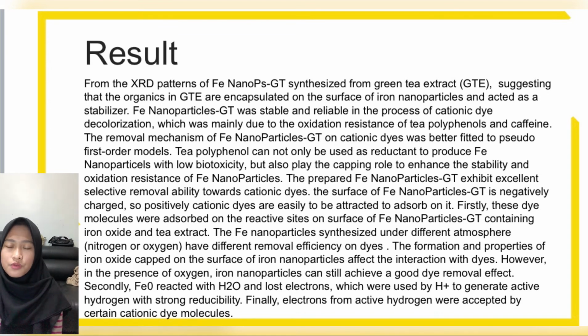synthesized under different atmospheres, nitrogen or oxygen, have different removal efficiency on dyes. The formation and properties of iron oxide capped on the surface of iron nanoparticle affect the interaction with dyes. However, in the presence of oxygen, iron nanoparticle can still achieve a good dye removal effect. Secondly, Fe0 reacted with H2O and lost electrons, which were used by H+ to generate active hydrogen with strong reducibility. Finally, electrons from active hydrogen were accepted by certain cationic dye molecules.